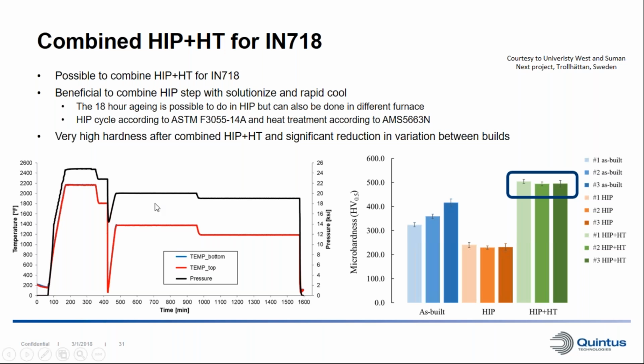As we can see on the lower left here, this is the cycle we have done in an actual HIP. So we have the conventional HIP cycle. We go down a little bit in temperature to the typical solutionizing temperature for this material. We cool down to room temperature, and then we heat up again to the dual step aging.